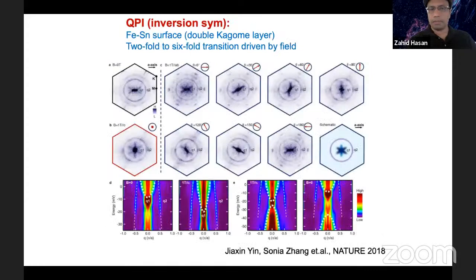One thing in this compound we found by surprise. It was not predicted in any theory. We saw that even though the lattice is threefold or sixfold, the quasi-particle interference is twofold, even without applying a field or anything. That was a bit surprising, but then when we applied a strong out-of-plane field, it recovered the sixfold symmetry. Whereas if we apply an in-plane field, then we see that this twofold axis we can rotate with a magnetic field, we can rotate the nematic axis. This is interesting because there is some strong correlation in this system that created a nematic state, where the electronic state is ignoring the lattice symmetry. It's in a lower symmetry state.